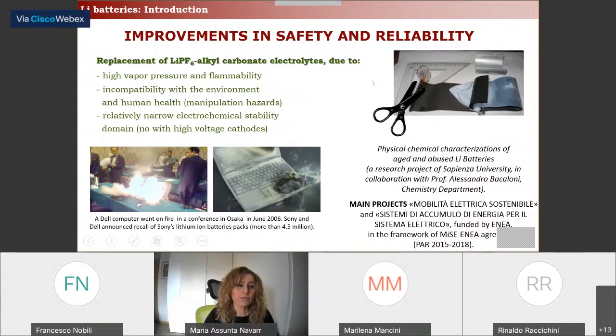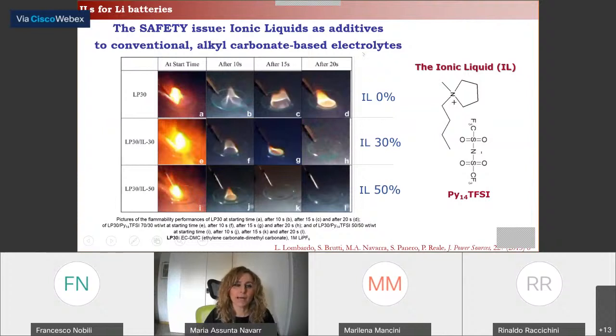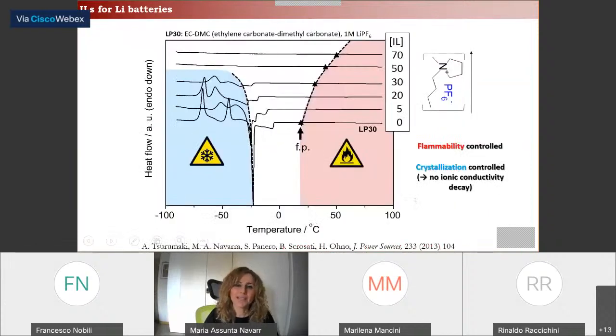A way to reduce the flammability of this conventional liquid electrolyte, such as commercial LP30, is the use of ionic liquids as flame retardants. In this study, for example, we demonstrated that the pyrrolidinium-1,4 TFSI ionic liquid can act as a good flame retardant additive able to control the self-extinguishing time of the electrolyte. But ionic liquids are not only flame retardants. They can be conveniently used for a double positive effect, both at high and lower temperatures.